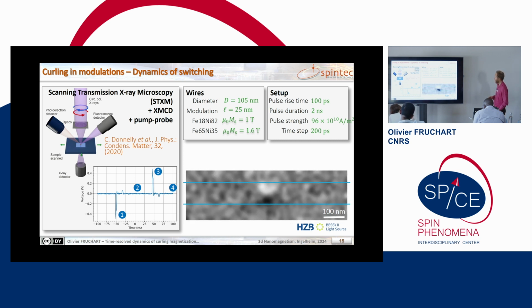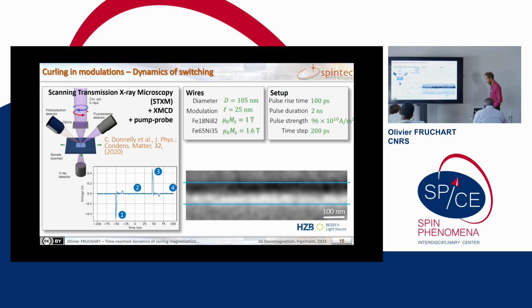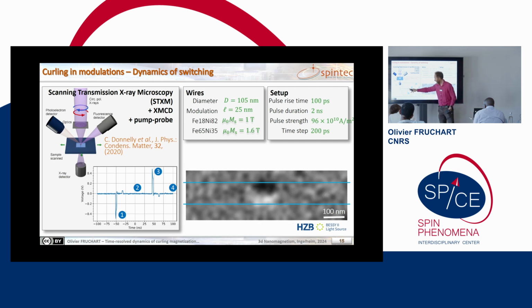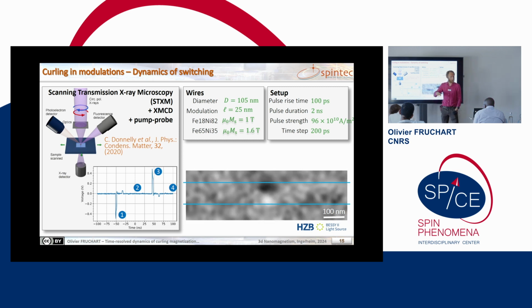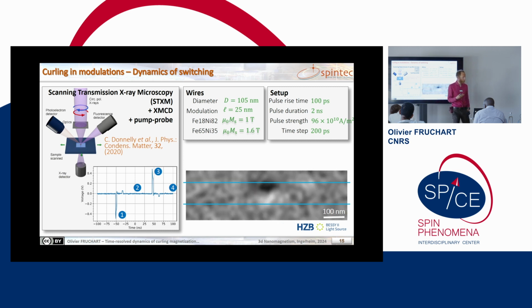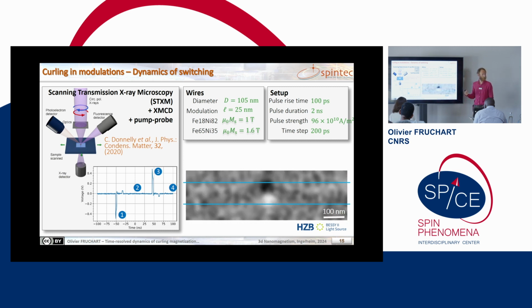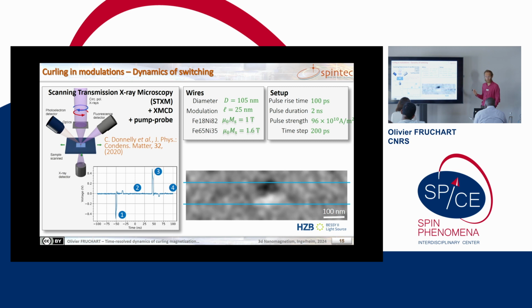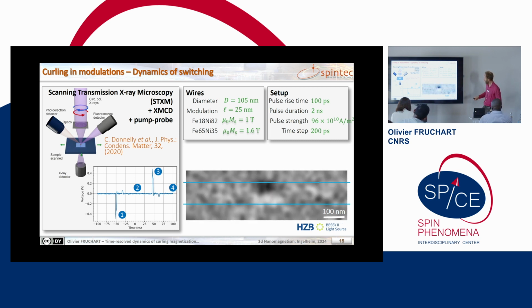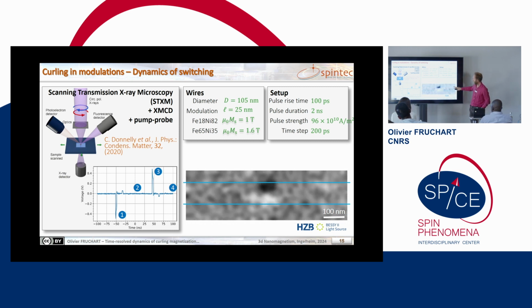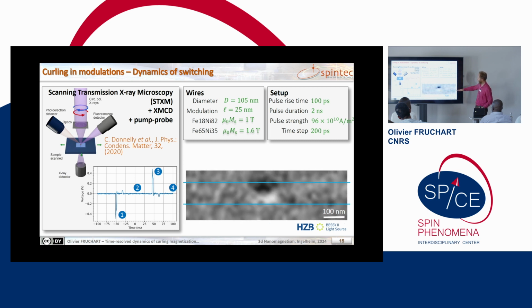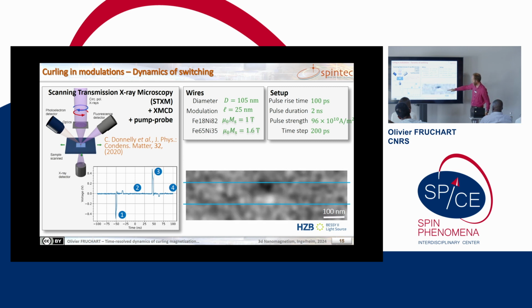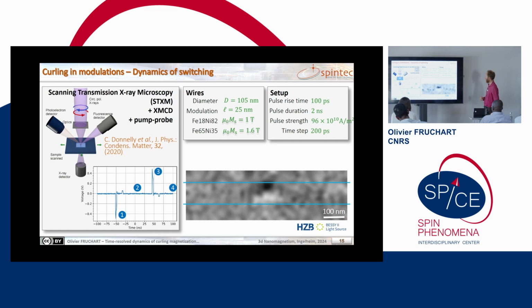So again, we try to have some time-resolved measurements. So what we do, always the same, some rest to make some imaging, and also to allow the wire to cool, because we are sending pulses with density of the order of 10^11 A/m². So you see it is black and white, and during the pulse, you will see that with the state, you will see white and black. So let us wait a few seconds.